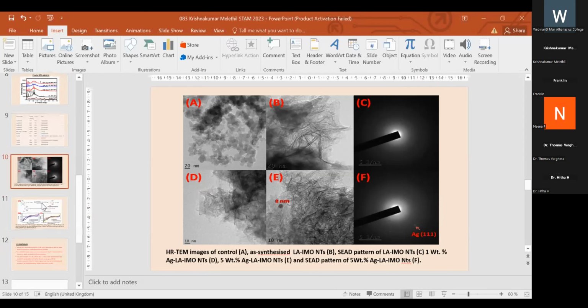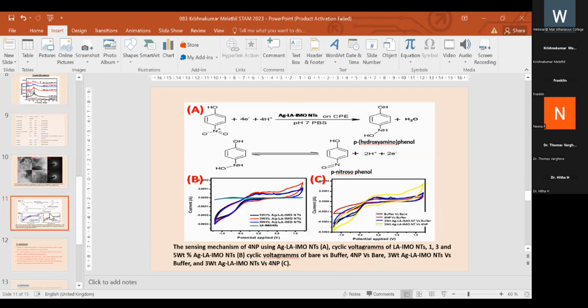And finally, we are going to the electrosensing part. In the electrosensing part, we can say that LAIMO is actually performing as an insulator, but by Ag nanoparticle loading, it becomes conductive. So we can say that our work is successful, and we can show that electrosensing is possible by loading a small amount of silver on imogolite nanotubes.